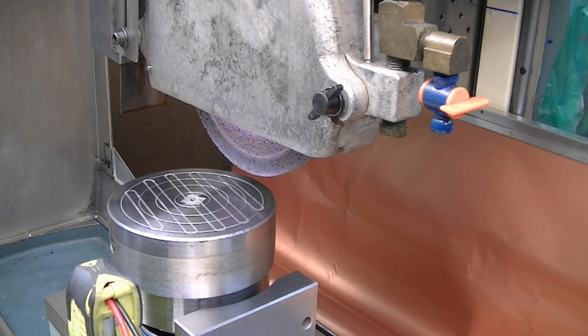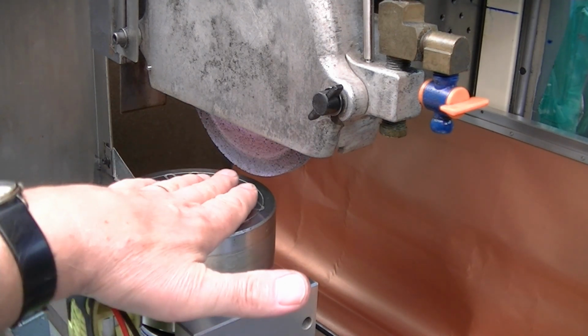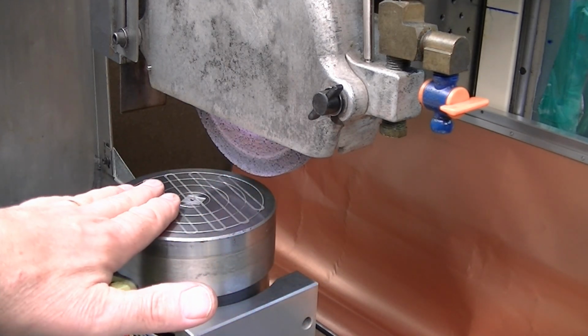And the other aspect of grinding, when you're reciprocating grinding, if you have a grinder that's using oil film, the speed of the traverse affects the actual oil film height. Yes, we're talking very small numbers, sub-tenth numbers of difference in oil film height depending on your traverse speed, but it's there. So that affects the shape of your part also. So a ball bearing style or an air bearing style of rotary spindle can give you very, very flat parts.